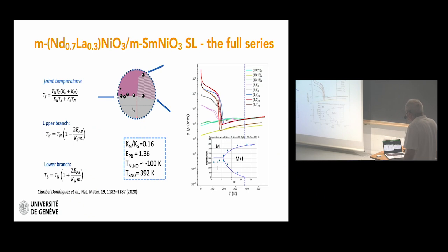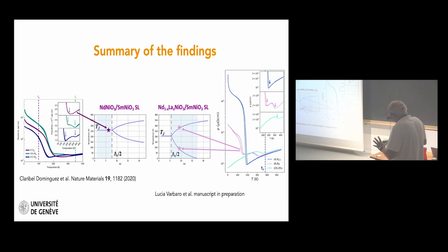And you see the full series here, and it's been analyzed using the same theory. So if we compare the two results, for the first, neodymium nickelate and samarium nickelate, the interesting region was the region here with the coupled transitions. Here for these solid solutions, it's more this middle region where we see two transitions as the single layers are still metallic.